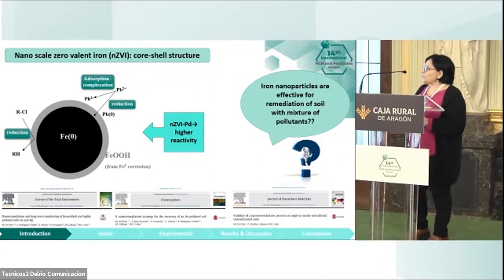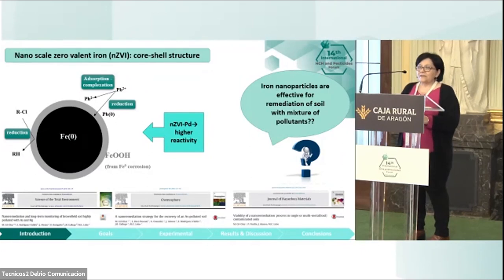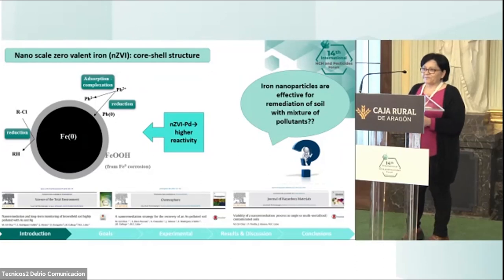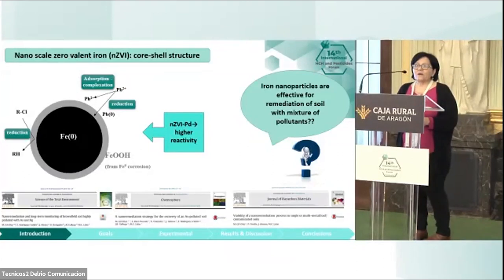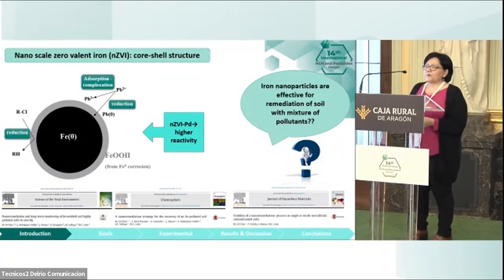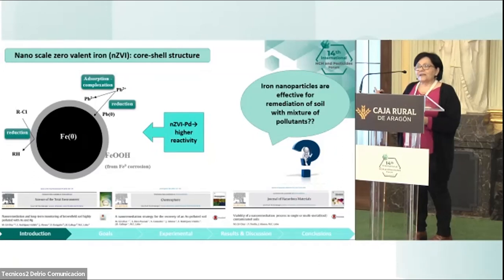These nanoparticles in contact with the contaminants can lead to adsorption or reduction. Zero valent iron nanoparticles can also be used with palladium. According to the articles published and the tests, this leads to a higher reactivity. So the question that we posed ourselves was, can we use these nanoparticles that are giving good results with heavy metals in order to decontaminate this soil, which has a mixture of pollutants with PCB and chromium?